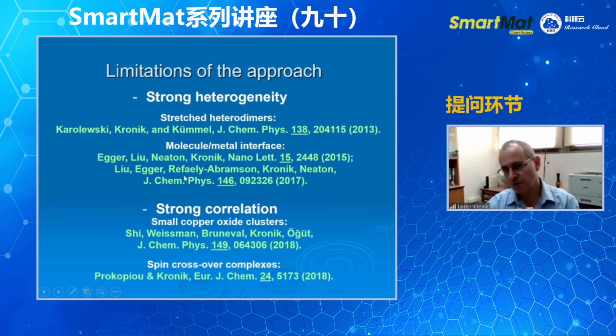So now to answer your question more directly, if I have a self-assembled monolayer on the metal, or on a semiconductor for that matter, I now have two different sources of gap renormalization. One is from the dielectric response of the semiconductor or the image charge of the metal, and one from all of the neighboring molecules. I need to sum up these effects correctly if I am to get the overall renormalization correctly. And that's exactly what's being discussed in these two articles here, the Nano Letters and the Journal of Chemical Physics articles.